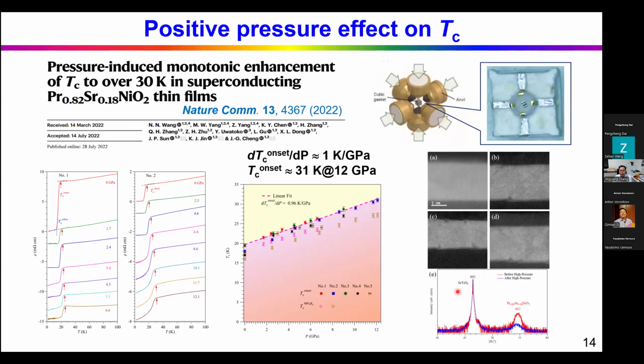But it turns out it's not very easy to measure the resistivity on these nickelate samples, because this infinite layer sample was obtained by reducing the corresponding perovskite phase. The apical oxygen is removed, so it's very fragile and it's not easy to perform high pressure measurement. Finally, we used the cubic anvil cell. We put the thin film in a liquid pressure medium. I will explain in detail this high pressure technique.